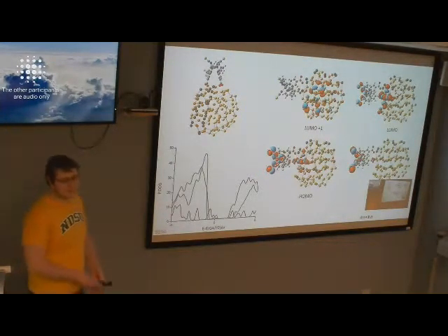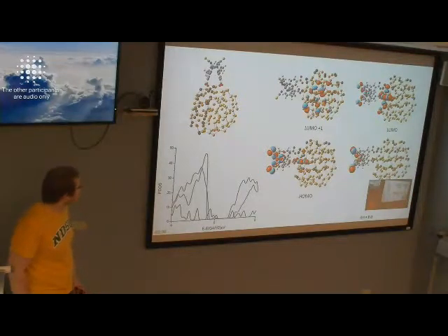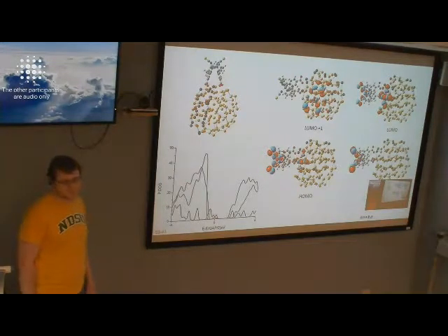So putting ligands on the leads or cadmiums will probably prevent this bending. Also putting a proton on one of the carboxylate groups will definitely minimize this effect as well, although we still will probably have cyanides to contribute.